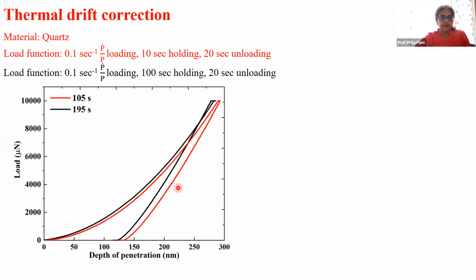So here is experimental data from quartz, which is not viscoelastic. So we can't blame viscoelasticity for any of these results. The experiment is done in a P dot by P controlled mode, 0.1 per second in both the cases. The only difference is the red curve. We load it up to 10,000 micronewton, 10 millinewton. We hold it for 10 seconds and we unload it in 20 seconds. Here we hold it for 100 seconds and we unload it in 20 seconds. And you can clearly see this black curve is not making a lot of sense.